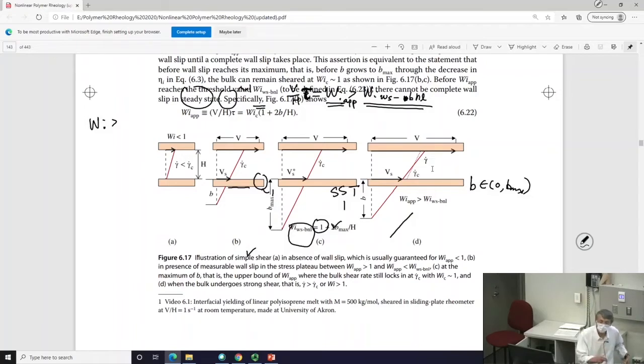if you were to understand the nonlinear aspect of shear, in other words, strong shear condition, you can see there's no way out but to first be able to handle what happens with wall slip. In other words, if wall slip is something you cannot account for its correction, you cannot proceed to look at the nonlinear response in the bulk, because I just indicated to you up to this point, all the response is only slip. So this, I think intuitively it's very straightforward. The system simply, when you apply higher and higher shear, if it's able to slip, it will simply not try to build more stress, but try to absorb this additional amount of shear by approaching the maximum amount of slip.